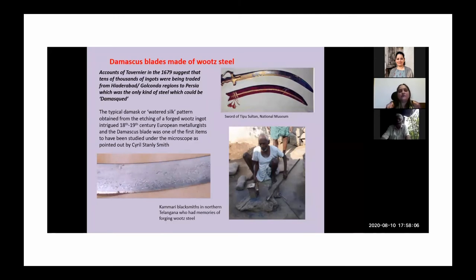And in fact, the account of Tavernier in 1679 suggests that tens of thousands of these ingots were being traded from the Hyderabad or Golconda regions to Persia. And he kept insisting that this is the only kind of steel which could be damasked, which could get these kinds of patterns. So this was clearly because they were able to get the true wootz steel in some of these regions here in Golconda and so on. And this was apparently a very widespread activity, almost like a semi-industrial enterprise there.